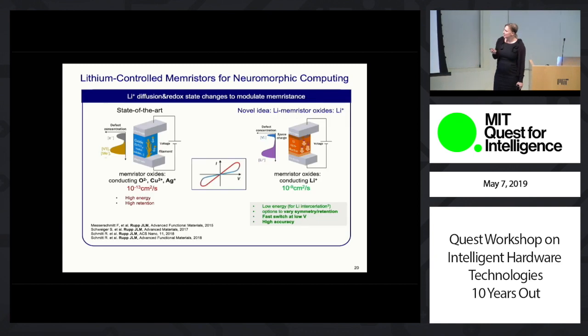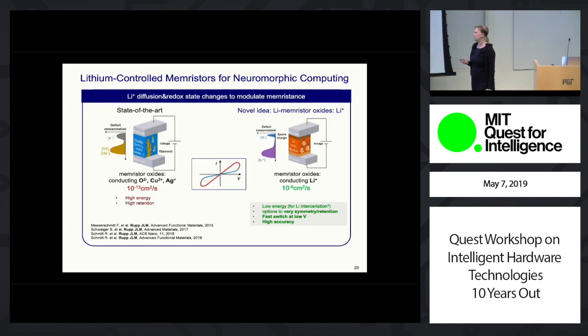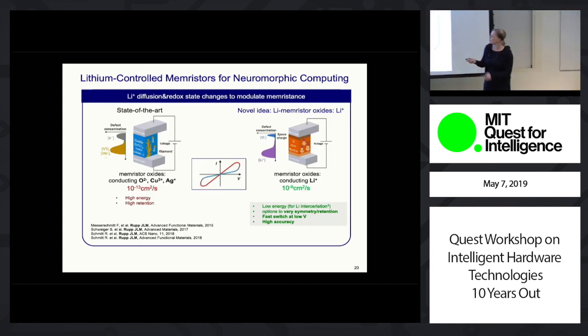There have been some recent ideas in the field to move away from those ions that I showed you before, which are very commonly oxygen, copper, and silver in these either filamentary or interface-based memristors, and to look, for instance, at ions that could migrate much faster. Can we make, for instance, a bipolar interface memristor, but use ions that have much faster diffusivity, like lithium? Lithium is a great fellow.